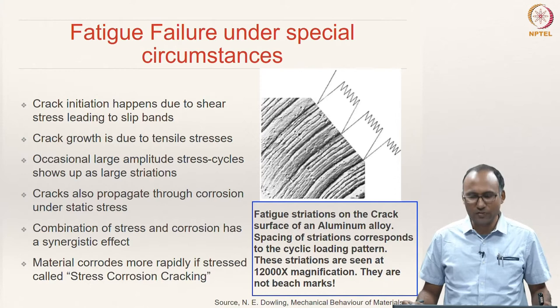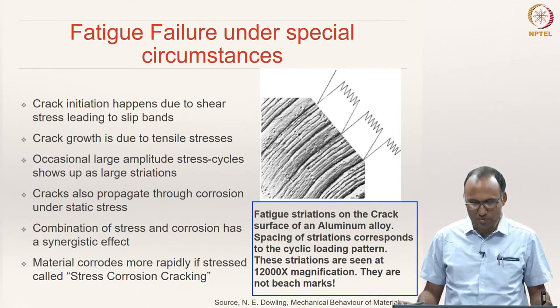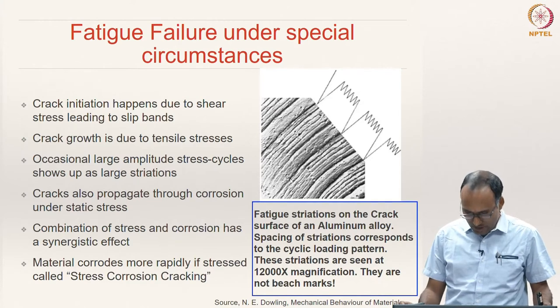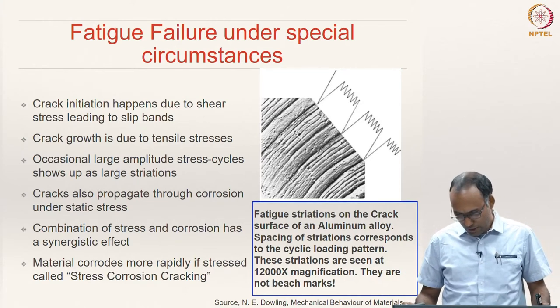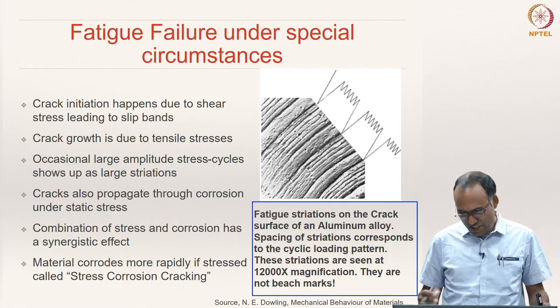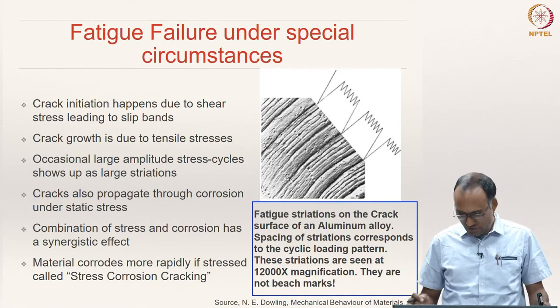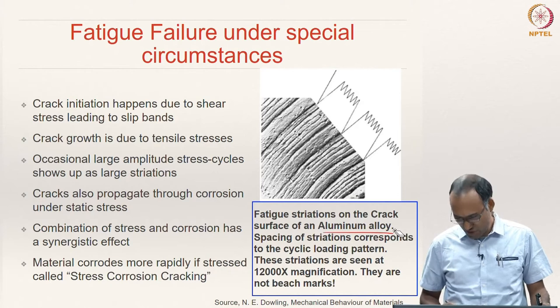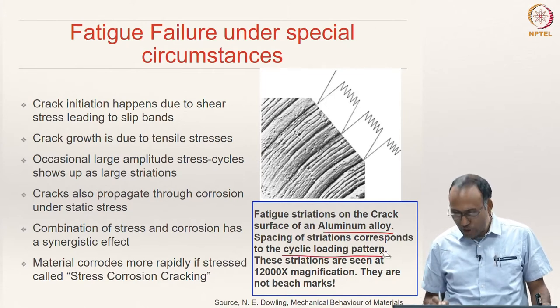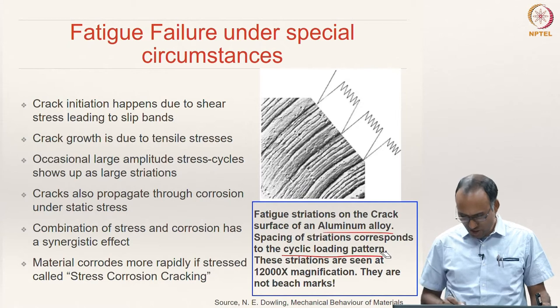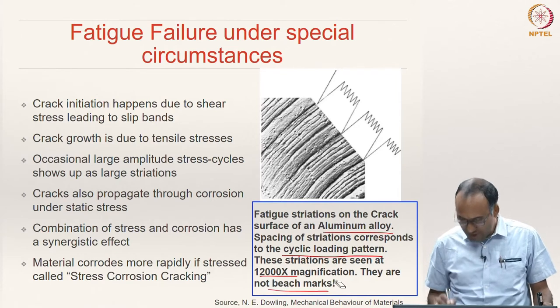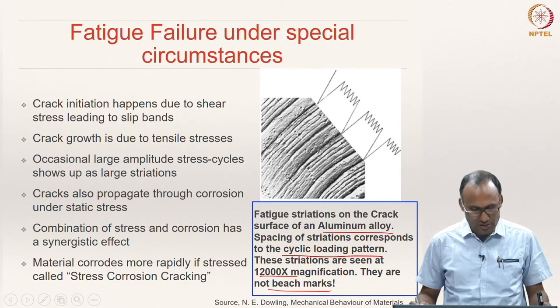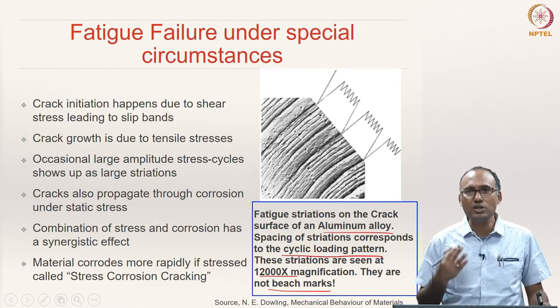Now we will look at fatigue failure scenarios under some special circumstances. This micrograph shows the striations on the surface of an aluminum alloy crack surface. There is a distinct spacing between the striations that corresponds to the cyclic loading pattern of the system. These striations are shown at 12,000x magnification and are not the beach marks we have seen before.